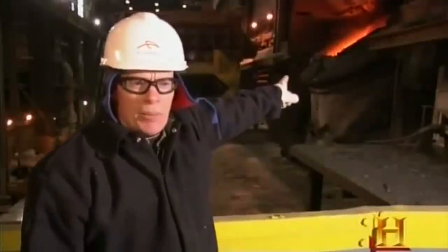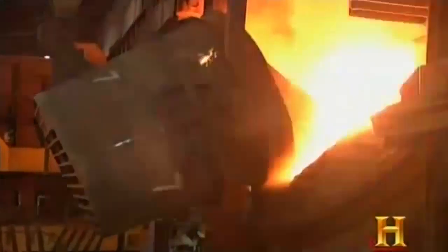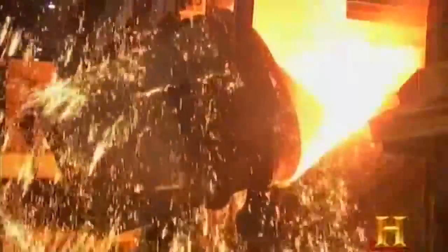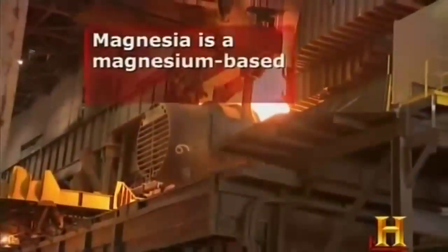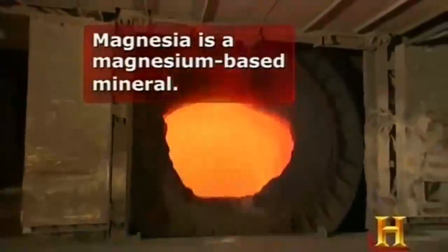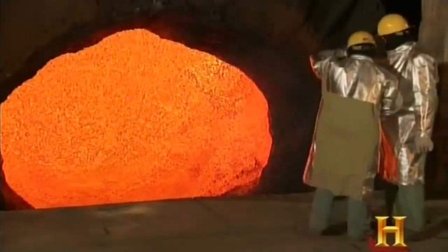Behind us here, you're seeing our number one furnace at the Burns Harbor Steel Shop. In the furnace, a magnesia carbon lining is the protection of choice. The combination of magnesia's high melting point of roughly 5,400 degrees Fahrenheit and carbon's strength make them ideal for taking on the super hot. It's about $1.5 million worth of brick, and that brick acts as an insulator between the 3,100 degree steelmaking temperatures and the steel shell on the furnace. On the outside, the shell is between 300 and 350 degrees Fahrenheit.